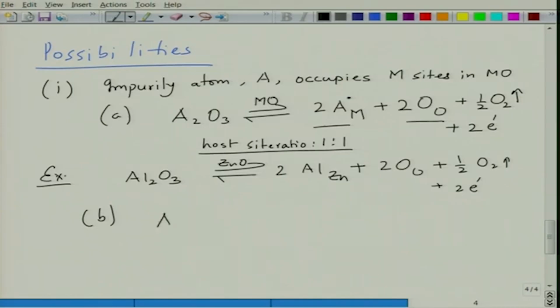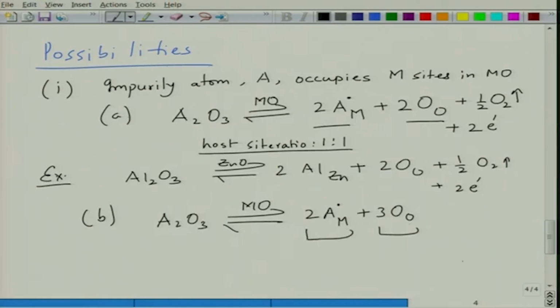The other possibility is A2O3 is in MO, 2AM plus let us say all the 3 oxygens go to oxygen site. Now, the site balance is disturbed because you have created 3 oxygen sites, but you have only 2 metal sites, which means one of the metal sites will be vacant. So, this is ionic compensation. You will create metal vacancy.